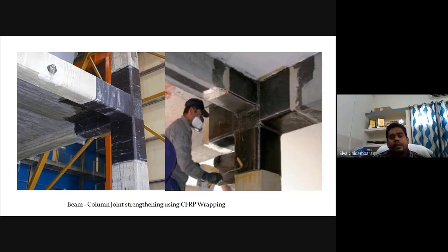If you look at the FRP studies, failure of FRP will almost always be in terms of delamination. Because the modulus of your CFRP is very, very high compared to glass, glass generally will rupture. So predominantly CFRP is preferred for strengthening purposes like this. When the element is subjected to a large amount of lateral force, monotonic, etc., the fiber will take the stress up to a certain limit. Later, the interface matrix, the epoxy, loses its strength and bonding ability, and it will not transfer the force to the FRP, and the FRP will delaminate. FRP will delaminate because the epoxy which we have used is not able to transfer that much force.